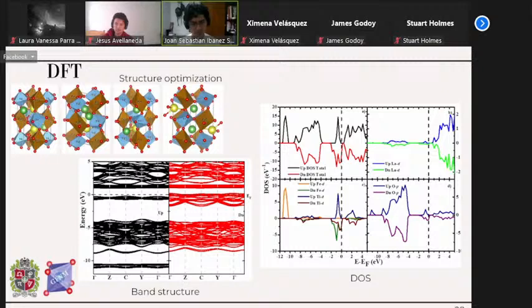With this structure, Professor De Luque made the calculations of the bands that you can see at the bottom. In particular, in these bands, you can see that at the Fermi energy, which is denoted by the dotted line, the conduction is different for up spin and for down spin. We have semiconductor behavior for up spin, and metallic behavior for down spin. So we have a ferromagnetic semiconductor that could be used for spin valves, or to construct gadgets alike in the spintronic industry.